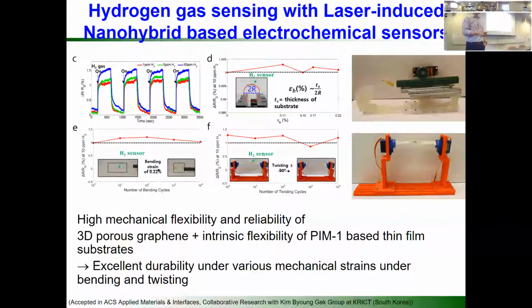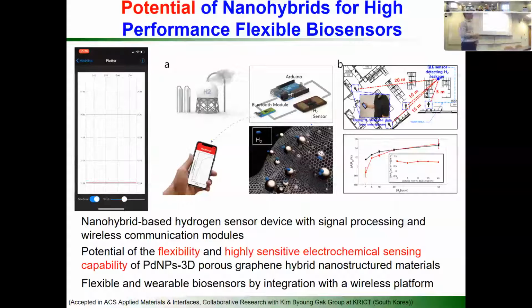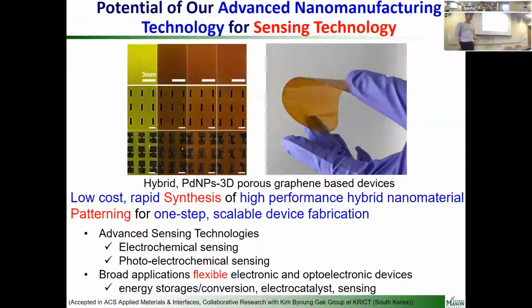The material is mechanically robust. Imagine that the nanoparticles are on top of the graphene, and as we bend it, the nanoparticles will move around. But as we have a coherent material, what I mean by coherent is that the nanoparticles are embedded like chocolate chips in a muffin. Then it is robust and reliable even to bending. So we make those types of sensors, and one of the applications is electrochemical sensors. This has potential for scalable and large-scale production of the material, and at the same time direct application to wearable and flexible sensors.